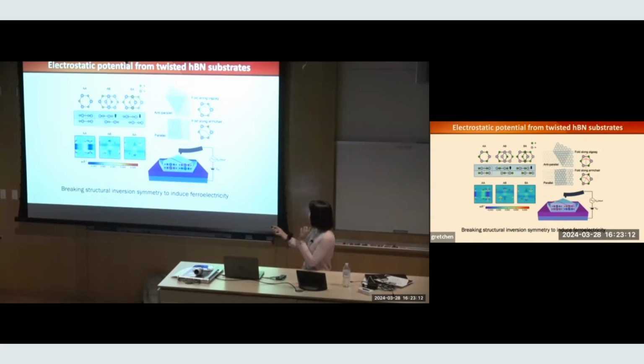So again, there are high symmetry stacking points, right? The A stacking point, the hexagonal is on top of hexagonal. They obey the inversion symmetry. But if you move over to a different high symmetry point, now you can see the inversion symmetry is broken, right? In this, both AB and BA stacking break the inversion symmetry, and at the twisted interface, you would actually form a spontaneous electrical dipole.